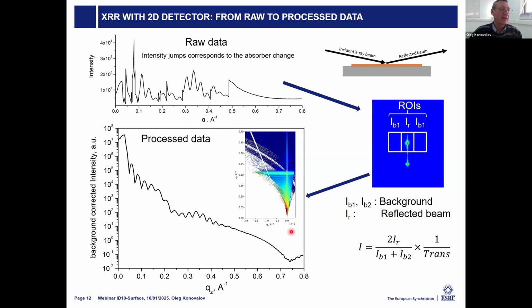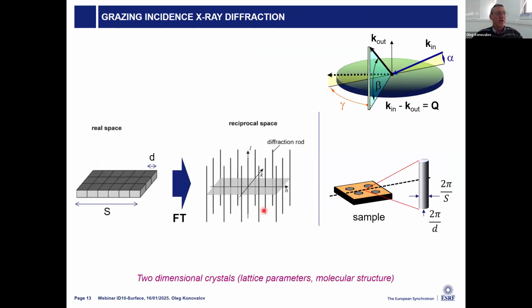And here, this is a reconstruction of the reciprocal space map during the reflectivity measurements, when we take all the intensities along the QZ direction and stitch them together. This is additional information we can get from the sample: not only the reflectivity curve, but also the diffuse scattering around it. For grazing incidence diffraction, if we have a two-dimensional system, in reciprocal space after the Fourier transformation, what is big becomes small, and what is small becomes big. So instead of points, we have rods normal to the plane of the sample. This is in fact the Bragg position if there is a two-dimensional ordering. From this, we can learn information about 2D systems.